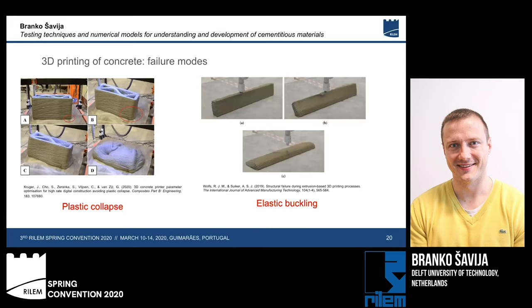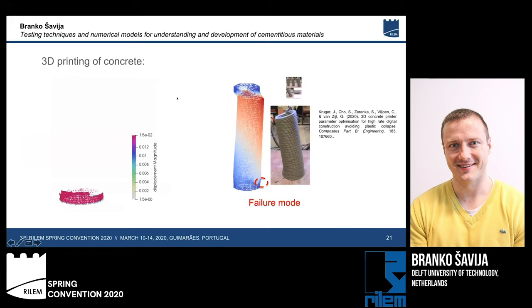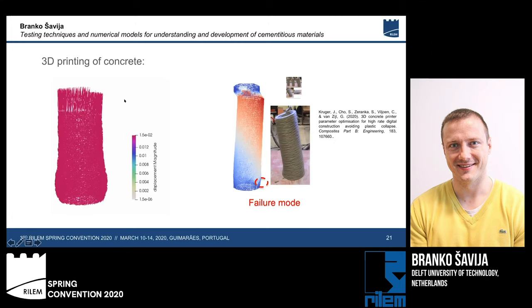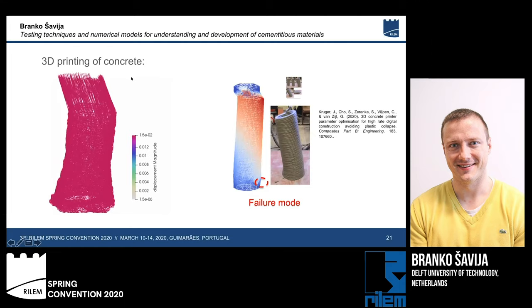process. And if we are to model 3D printing processes of cementitious materials, our models need to be able to capture both of these modes, the plastic collapse and the elastic buckling of our 3D printed material. We are currently developing models, such as the one shown on the left-hand side, which should be able to do this. So we can build our material layer by layer, as shown here. And we see, as we build more and more layers, we get more and more deformation, because the material, although it hardens already at the bottom, is still relatively in a fresh state. And finally, if we add enough load, the material will collapse.